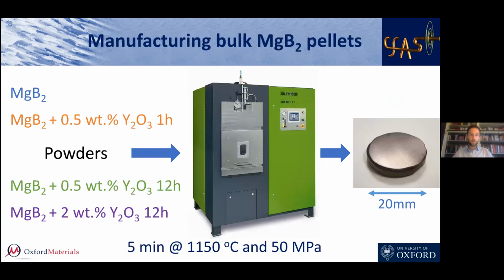So the second step was obviously to try to see if we could reprecipitate and have this microstructure. So we had a few powders. One that had 0.5% of yttria, ball milled an hour, one with the same quantity but ball milled for 12 hours, and one which had slightly more yttria. Again, we put it in the field assisted sintering machine, and then we have that pellet that we can analyze.